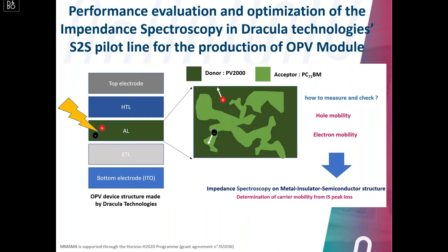So in this slide, I will just tell you a little bit again about the device structure used by DRACULA technologies. Concerning the active layer, in general it is composed of two different materials, the donor and the acceptor, a polymer and fullerene derivatives, which are in general randomly distributed inside the bulk. Today it's known that the mobility of hole and electron is not the same, knowing that the hole should be transported by the donor and the electron by the acceptor. And if the mobility of the hole and the electron is not the same, it can create some problems in the performances. To control and to determine these values, we need such a technique, the impedance spectroscopy.